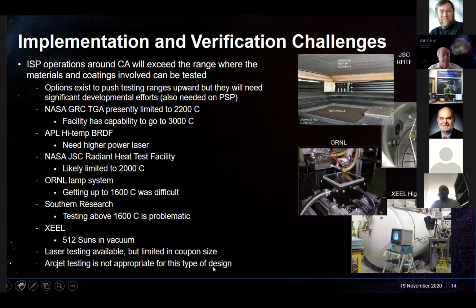You're not only trying to do the test, with graphite heaters and radiant lamp heaters, we want to do this whole test in vacuum. Again, the vacuums you get are kind of difficult, so we're not talking about high vacuum usually, we're talking about medium vacuums. When we were testing at Johnson, we would see charring of the carbon that was in the system. That was probably in the couple of torr vacuum levels.